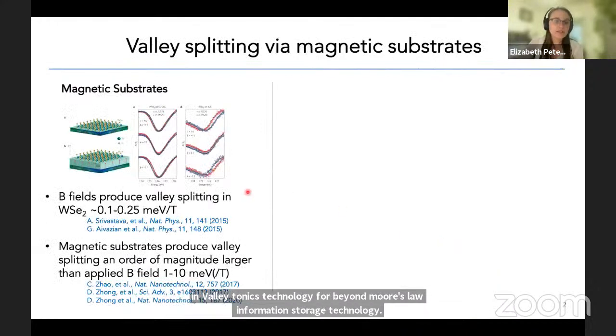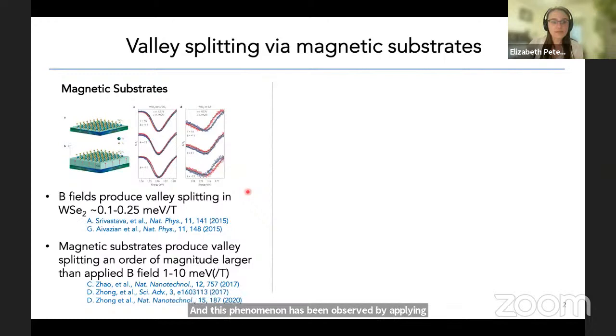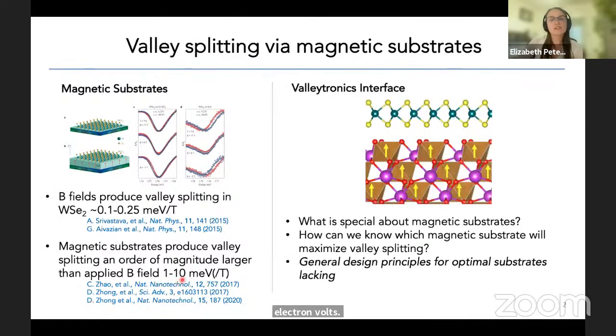This phenomenon has been observed by applying magnetic fields to transition metal dichalcogenides and can produce valley splittings on the order of 0.1 to 0.2 millielectron volts per Tesla, which is quite small. Magnetic substrates, however, are capable of producing valley splittings an order of magnitude larger than applied magnetic fields, on the order of 1 to 10 millielectron volts. This begs the question, what is so special about magnetic substrates? Why are they so much more effective than magnetic fields? How can we know which magnetic substrates will maximize valley splitting? What this comes down to is that at this point, general design principles for optimal substrates are a piece of information that's really lacking in the community.